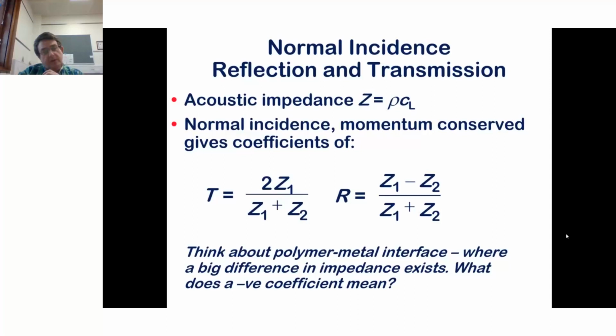But if you think about, say, a polymer-metal interface, well, a polymer has a low impedance, and the metal has a high impedance. What does a negative reflection coefficient mean? What it means is that something which was originally a tensile wave, something that is reducing the stress in the system, is reflected as a compression wave, so it changes phase. Hopefully people are familiar with reflection at interfaces and realize that sometimes you get changes in phase of light, changes in phase of stress waves when things are reflected from interfaces. And basically this is assuming normal incidence of the wave, so the wave going straight into the surface.